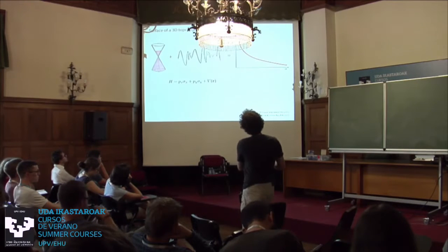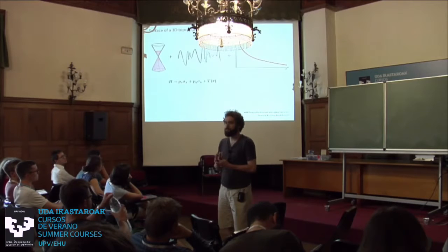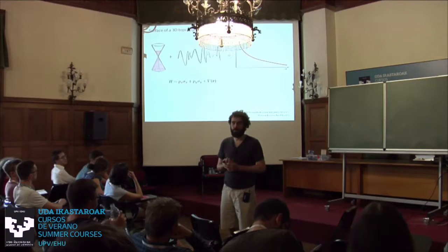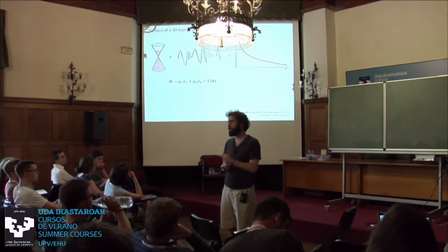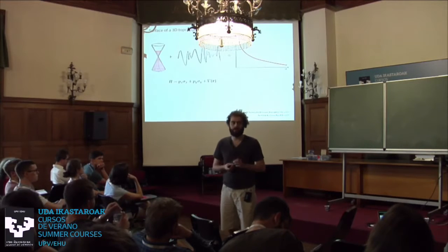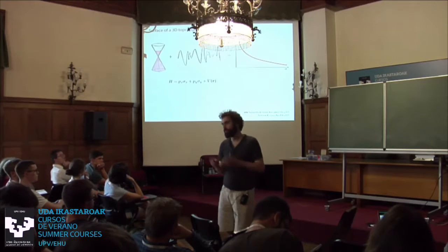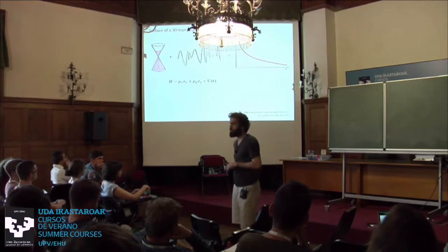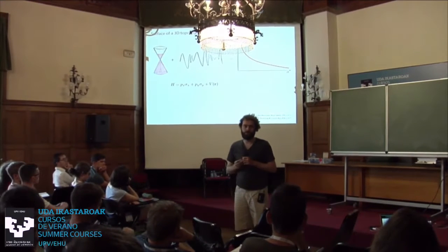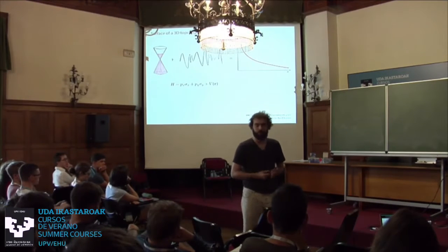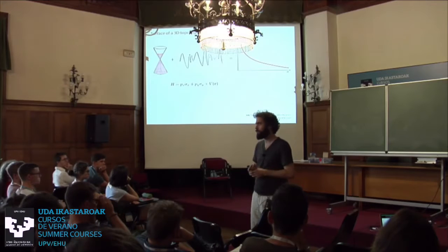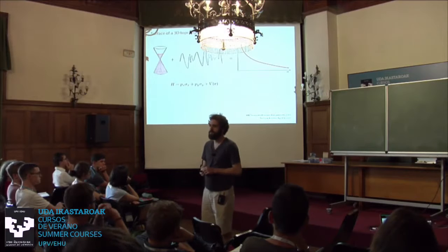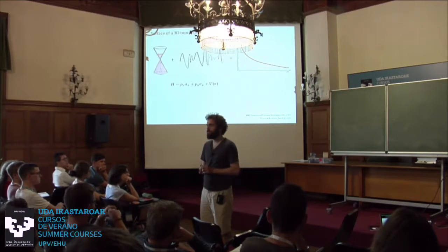But once you're here, all transport properties are just characterized by weak antilocalization. That means, in particular, that in a transport experiment, you cannot distinguish between a topological insulator surface or just some two-dimensional electron gas with spin-orbit coupling. So once you've done this, you have lost all signatures of topology in transport. So if you take a big chunk of a topological insulator and you're a transport person and you want to show that it's topological, you're screwed.